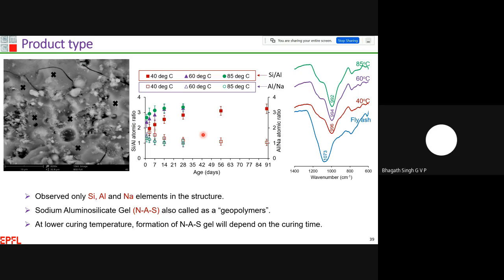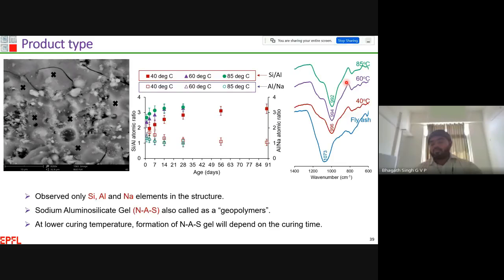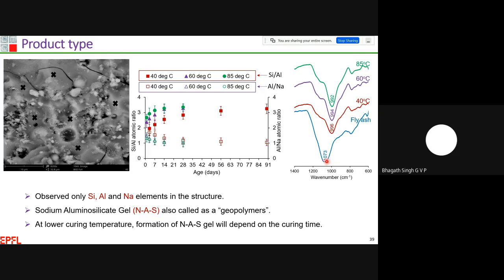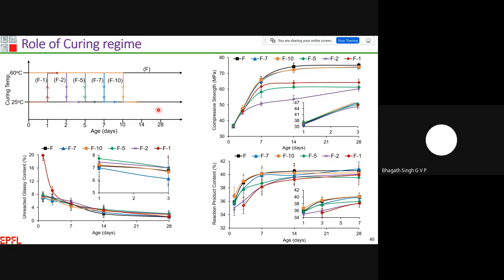I also used another tool, FTIR, to identify whether there is any change in the bandwidth once we varied the curing temperature to 40, 60, and 85. As you can see here, the pure fly ash bandwidth is about 1073. In the case of alkali-activated mixes, there is not much change, but the bandwidth shifts slightly to a lower wave number. Overall, this change in the bandwidth is representative of the formation of N-A-S-H product, and this is the glassy portion of the fly ash. It is also evident in our SEM results. The product type is clearly sodium aluminum silicate gel, with silica and alumina incorporated in the structure.